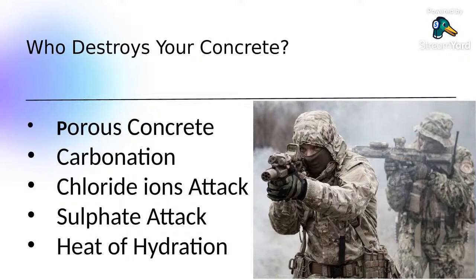The thinking today is you close all the doors and windows of this room so tightly that no enemy will come inside your room. And that is the thinking we have for protection of reinforcement steel, protection of your concrete. You stop the environmental agents at the gate of your concrete, so that there are no pathways, no calcium hydroxide leaching out, no pathways for them. Concrete becomes watertight. How do you measure that concrete is watertight? Coulomb value. How do you achieve the Coulomb value? Pozzolanic material like fly ash, hydraulic material like GGBFS, microsilica, ultrafine material.